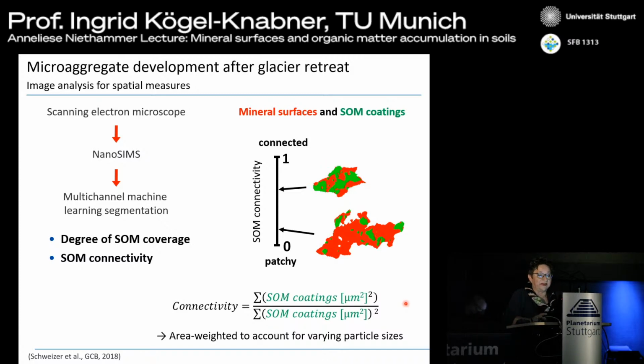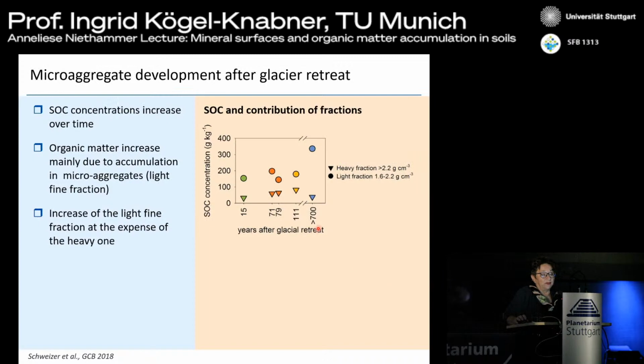And when we've done all this, we can look at these data. And first of all, what we see is two fractions. Both of them are generally heavy fractions, but the lighter one is 1.6 to 2.2 grams per cubic centimeter. This is the fraction that contains a lot of organic matter, because organic matter generally makes the minerals lighter. The heavy fraction, which is heavier than 2.2, contains very little organic matter.